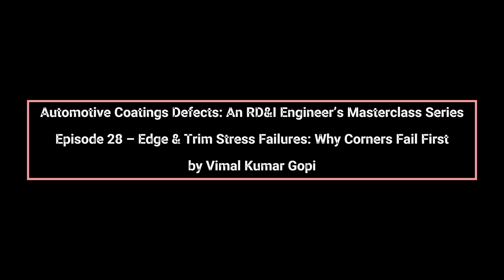Cure balance and crosslink density again play a central role. High crosslink clear coats resist chemical and UV attack, but have reduced elongation capacity, making them brittle over edges. Low crosslink formulations are more flexible, but can be penetrated more easily by water, chemicals, or road contaminants. OEMs must optimize crosslink density to allow sufficient strain absorption without compromising long-term protection.